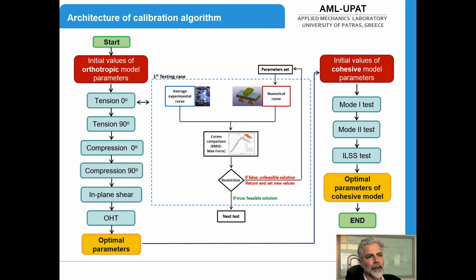For minimizing the parameter combinations, the calibration process was divided in 2 stages. The first stage includes the in-plane loading tests: tension in 0 and 90 direction, compression in 0 and 90 direction, shear test and open hole tests for the calibration of the orthotropic material law. Whereas in the second stage, which consists of the fracture tests and the ILSS one, we try to calibrate the cohesive zone model. This is clearly indicated in this diagram, where on the left you may see the calibration of the orthotropic material properties, and on the right you may see how the process of the calibration of the interlaminar fracture test and the ILSS test is taking place.